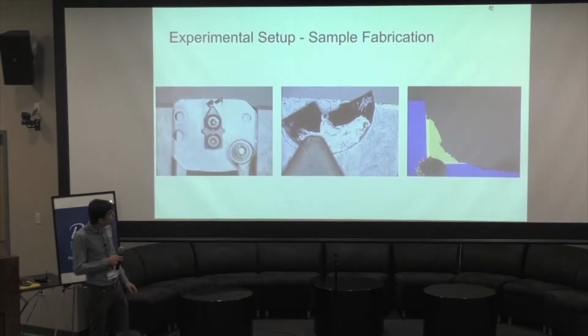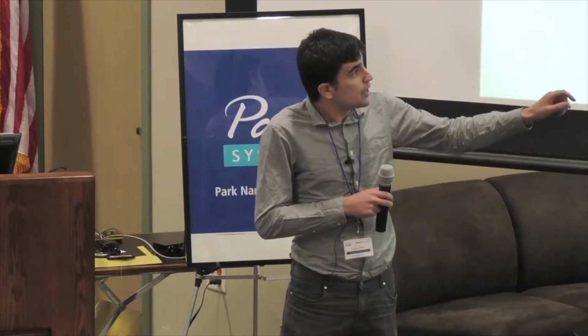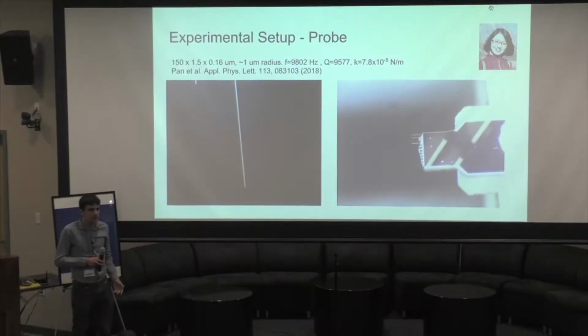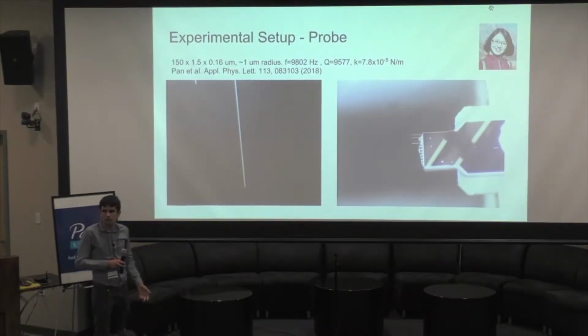We've attempted to ground the graphene with conductive epoxy, so we can potentially do some electrical measurements like varying the tip-sample voltage, but we haven't yet tested the efficacy of that grounding. For a probe, we're using an audio frequency cantilever made from single crystal silicon with a Q of about 10,000.